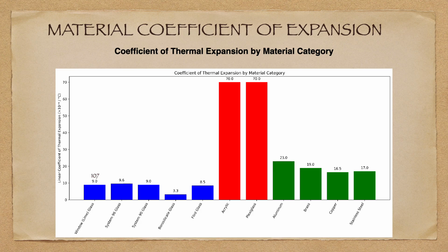If glasses are mixed with a markedly different coefficient, then they're much more subject to breaking and failing at a future date, sometimes immediately after making whatever object the artist is attempting to put together.